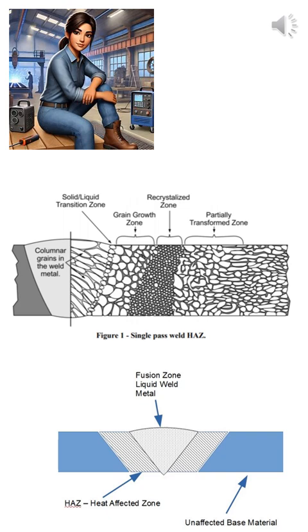Breakdown: Closest to the weld, you'll get grain growth - not good for toughness. Farther out, you might see grain refinement, which is usually better. And in some spots, you'll get annealing, softened material. The HAZ is often the weakest link in a weld because it can become embrittled and prone to cracking. The key variables here are heat input, cooling rate, and the steel's chemical composition.